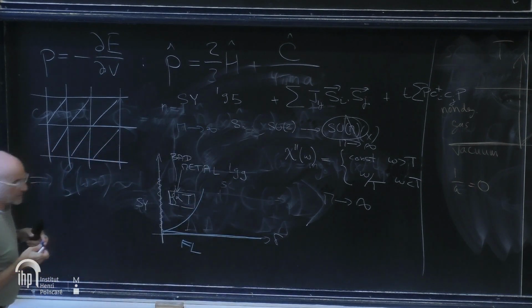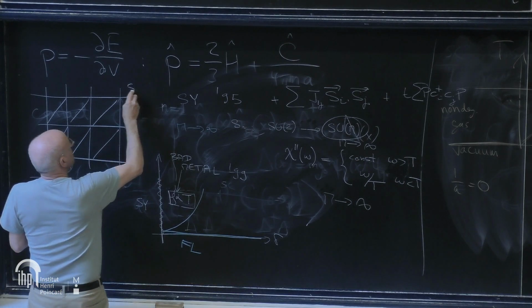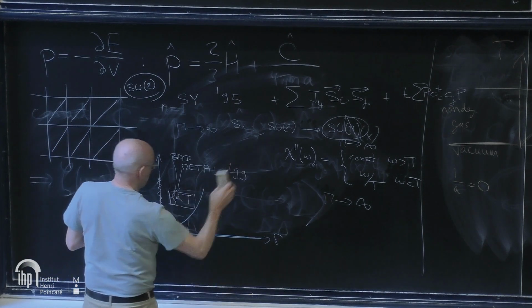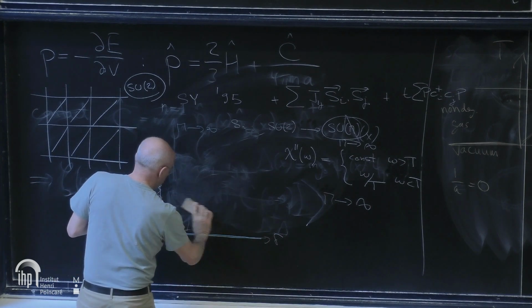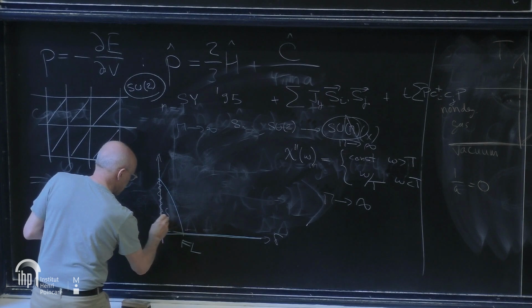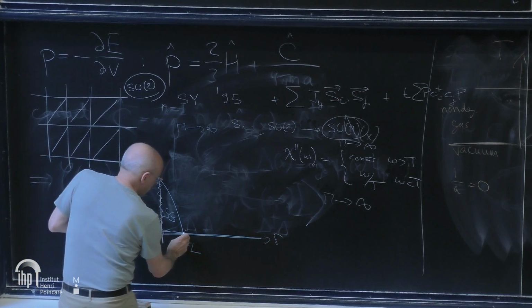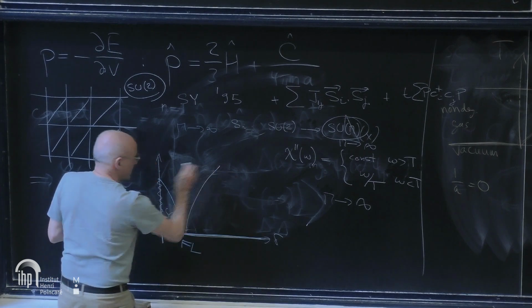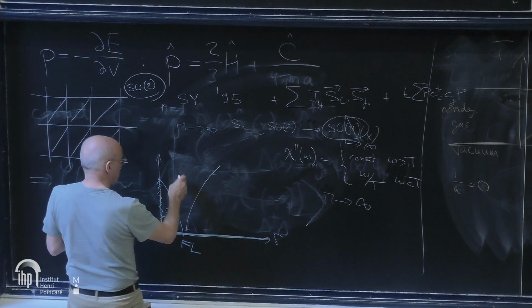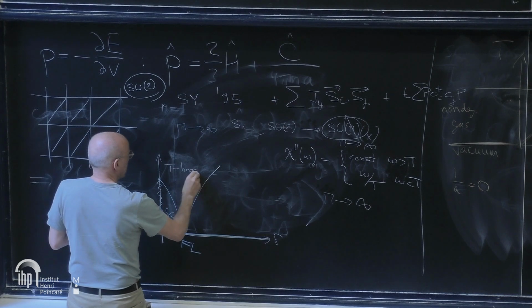Okay, but this is M goes to infinity, right? And what has been realized recently, in the past 5 years or so, is that if you now look back into the true system, SU2, this business that we had with Sachdev and myself is completely changed. What you get here is not a Sachdev-Ye liquid, it's actually a spin glass, as you would expect, because now we have just a random coupling Heisenberg model. A Fermi liquid here, indeed, and here a quantum critical regime, which is the melting of this metallic spin glass, in which, indeed, you can have T-linear resistivity down to T equals 0.